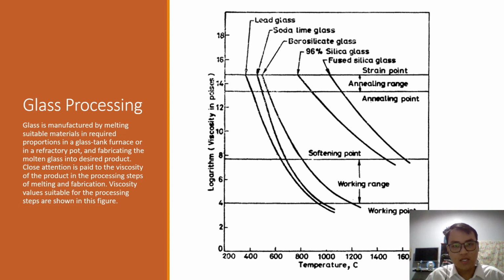Next is glass processing. Glass is manufactured by melting suitable materials in the required proportion in a glass tank furnace or in a refractory pot, and fabricating the molten glass into desired products. Close attention is paid to the viscosity of the product in the processing steps of melting and fabrication. Viscosity values suitable for the processing steps are shown in this figure. In the melting range, the viscosity of the product must be sufficiently low so that the gas bubbles can escape and homogenization can occur. The working range of viscosities is rather broad.